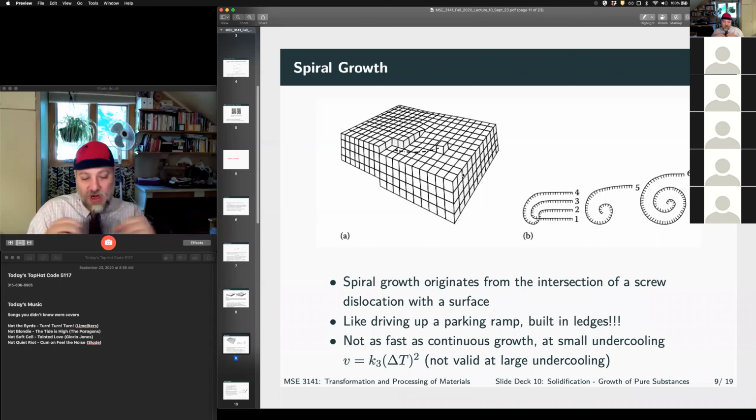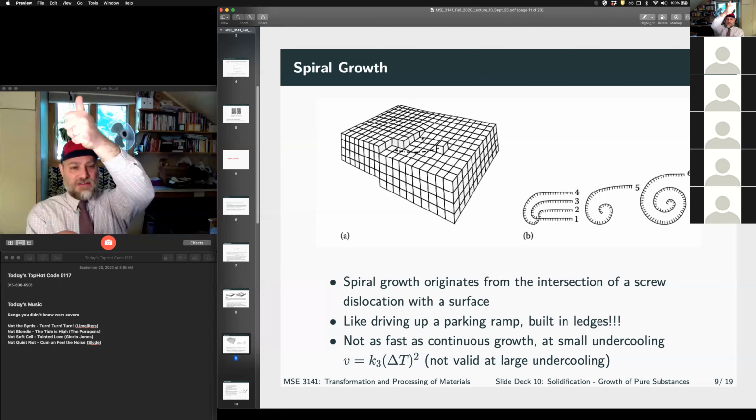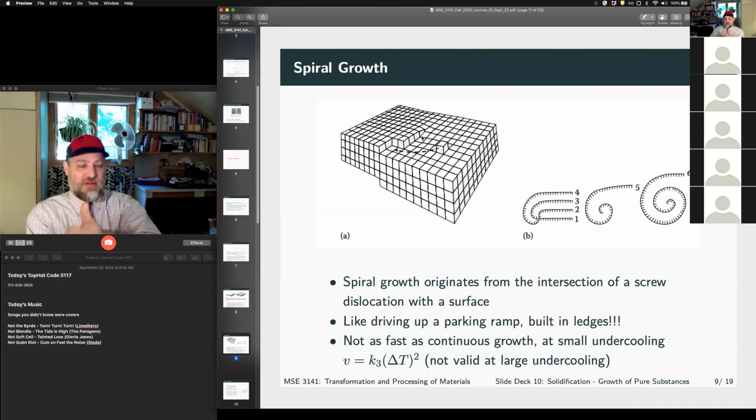It's not so hard to stretch a thin film, but as that gets thicker, the stress on that interface becomes greater and greater, and so one way to accommodate that mismatch of lattice in semiconductor devices is to nucleate threading dislocations that run perpendicular to your surface through the thickness of the crystal that you're growing.